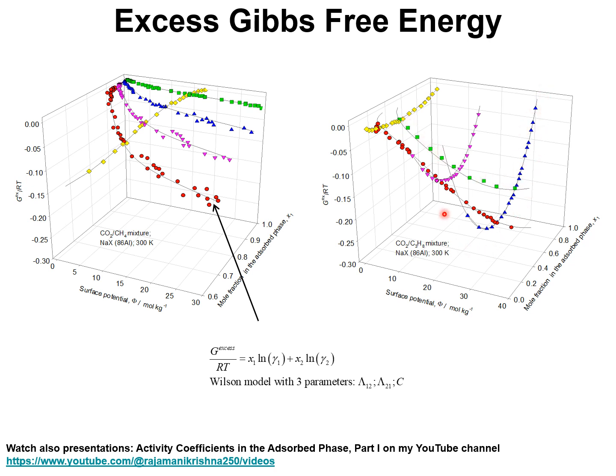And in these set of 3 CBMC simulations, the total bulk gas phase fugacity is held constant at a value, say 1 megapascal, 100 kilopascal, and this is 1 kilopascal total fugacity, and the composition in the bulk gas phase mixture is varied.